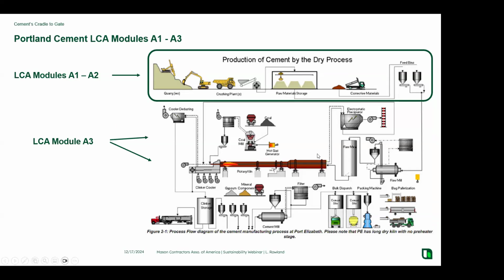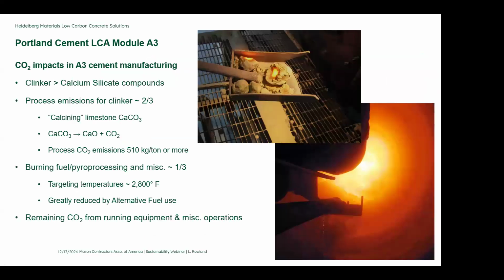That's where our impacts are, because we take those raw materials, we grind them up fine, we put them through a processing to get the limestone, the shale, etc., for our calcium and our silica to the right chemistry. We introduce that into a rotary furnace called a kiln. In those kilns, we heat up the material quite high to about 2,800 degrees to make clinker. Cement clinker is the product that we manufacture in a cement factory. That clinker is then taken and stored and then ground very fine with a little bit of gypsum, and that's essentially cement. So as we discussed, this is all part of our A3, the manufacturing module for cement manufacturing.